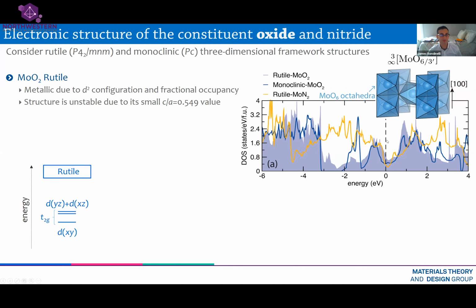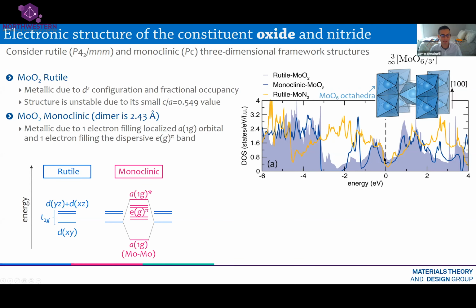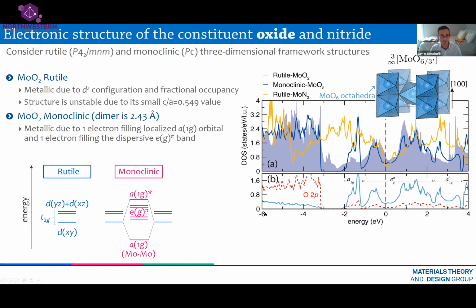And elementary band theory tells you that if you put the Fermi level in a band, meaning it's fractionally occupied, then you have a metal. And indeed, moly dioxide can be made and is a metal. And even if you distorted moly dioxide, that's what this dark blue curve is, the material remains metallic. The number of electrons at the Fermi level decreases, but it stays metallic. And that's because of fractional filling of this eg pi state. So this is a local chemical description of the electronic structure, but we don't really need to discuss it in any detail. This is the local orbital structure. If there are questions, I can answer them about this.